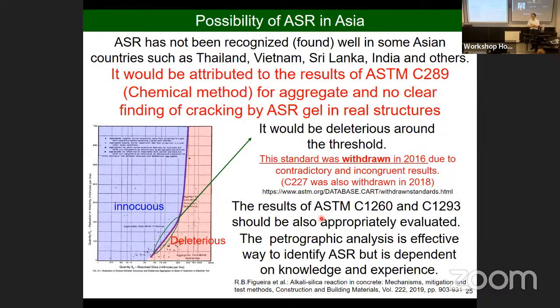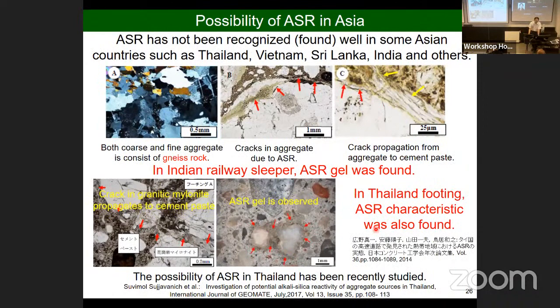But the problem is that what they judge as reactive or not reactive is just the chemical method. Probably you may know this standard was withdrawn in 2016, but they are still using it. Probably Dr. Yamada will explain that later, but anyway, the problem is they just use this kind of old method. And now, as Dr. Yamada explained, we have state-of-the-art technology to detect ASR. Actually, in the case of Thailand, ASR was found according to Dr. Yamada's work. Also recently in Thailand, the possibility of ASR has been studied. Probably ASR would occur even in India or other countries, Sri Lanka, but they don't check.